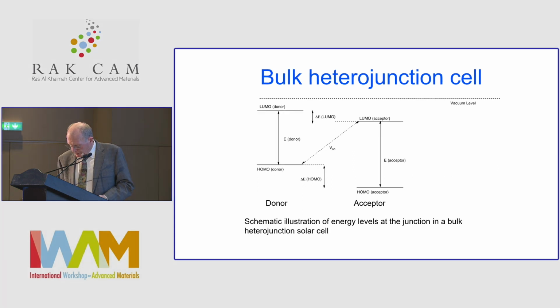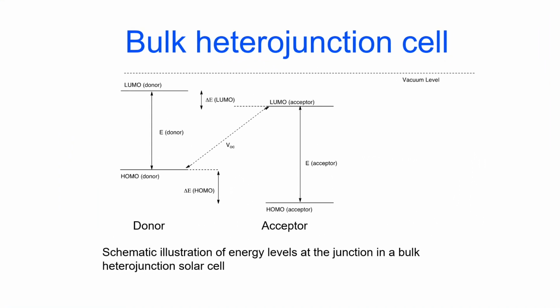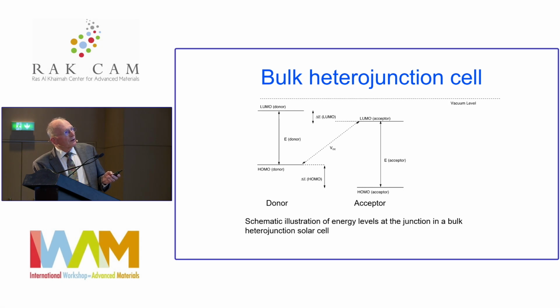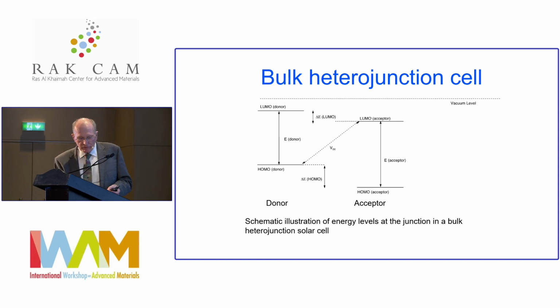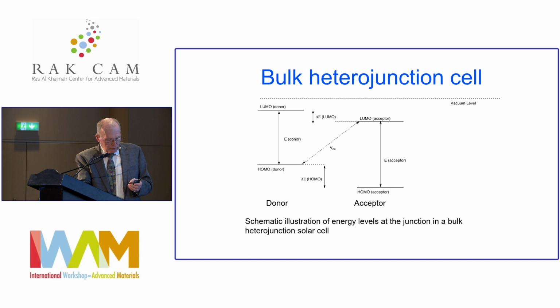And a very crude way of estimating what kind of open circuit voltage one is going to arrive at is to look at the occupied level of the donor material, the HOMO, the highest occupied level, which usually has 2 electrons in it, because excitation involves typically absorption of a photon to this lowest unoccupied level, and then, of course, charge migration to the acceptor. And so the difference between this HOMO here and the unoccupied level of the acceptor material gives a crude estimate of the open circuit voltage, but it doesn't tell you how much energy is needed to promote charge separation. So it's reduced by the energy needed to separate the charge at the interface, and that can be fractions of an electron volt, and they lower the open circuit voltage.